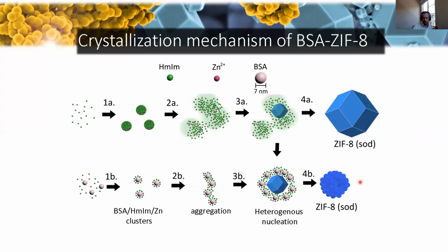That's why it caps their size out, and that's why you have this really rough surface morphology that we saw in the SEM images at the start, because that's really dictated by the size of these precursor particles.